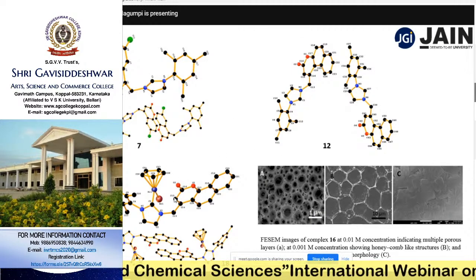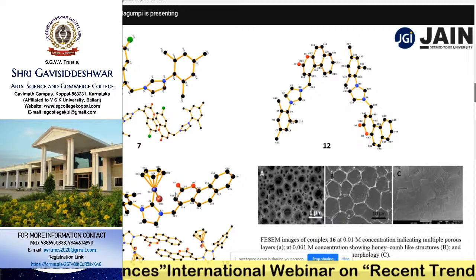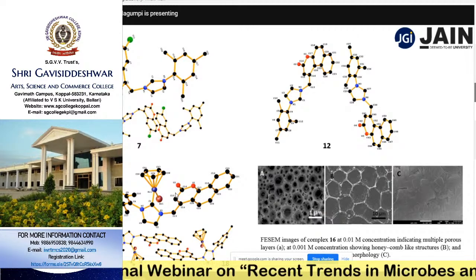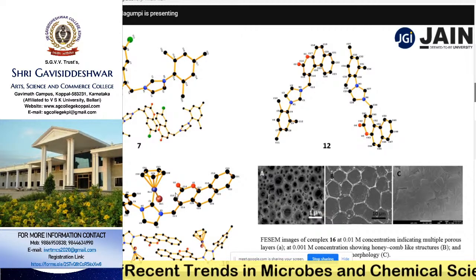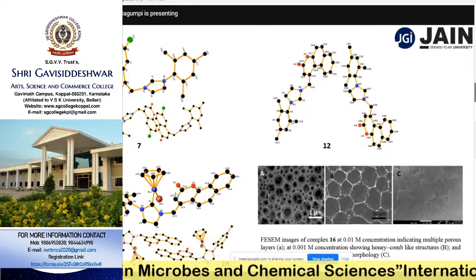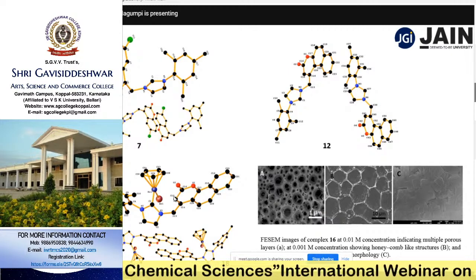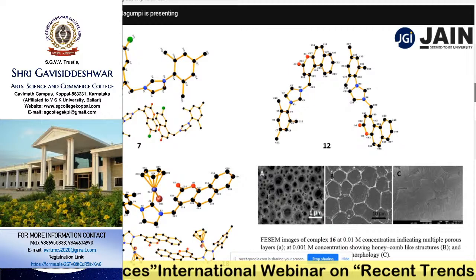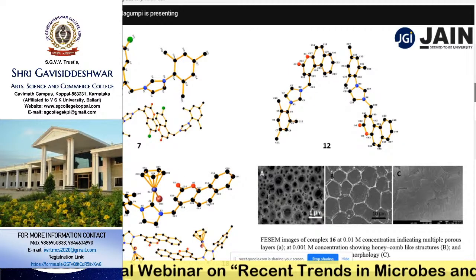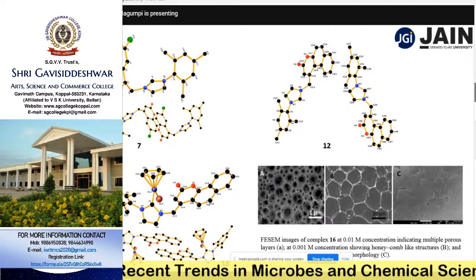We have analyzed this material. These materials have been drop casted on the glassy carbon electrode, right? Electrochemically, we want to evaluate the glucose sensing application of these complexes. Hence, these complex solutions have been drop casted on the surface of the glassy carbon electrode, which is the working electrode in CV experiments.